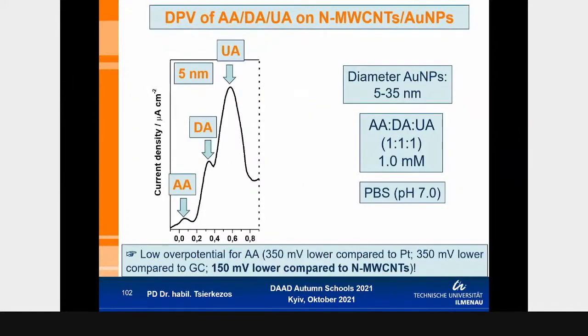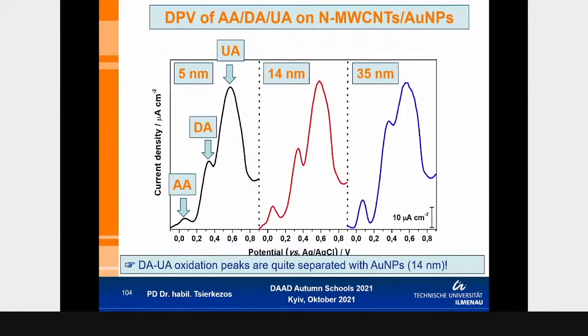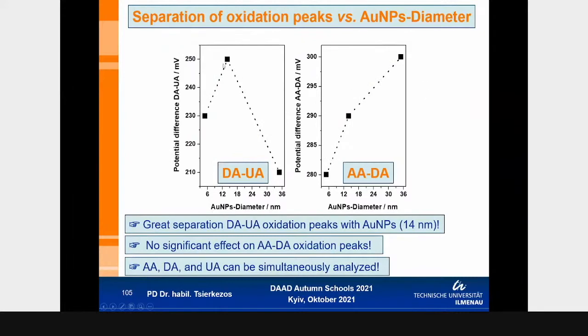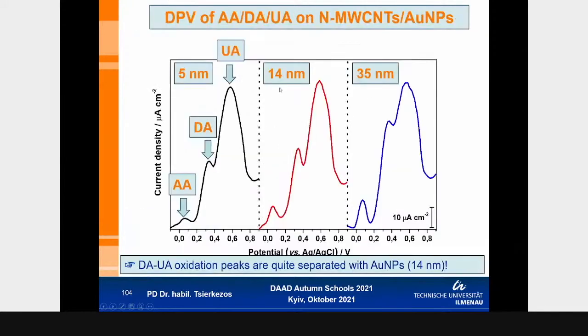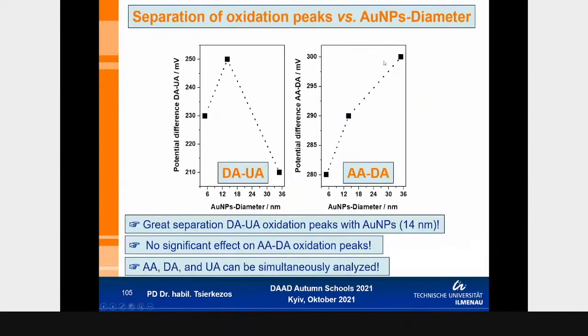And we have done the same by using differential pulse voltammetry, with different kinds of gold nanoparticles with different diameters, and we have observed that the greatest potential difference between dopamine and uric acid lies at about 250 by using the 14 nanometer nanoparticles, and the greatest potential difference between ascorbic acid and dopamine lies at about 300 with nanoparticles of size 35 and about 290 with nanoparticles of 14, which I think is enough for their simultaneous analysis.